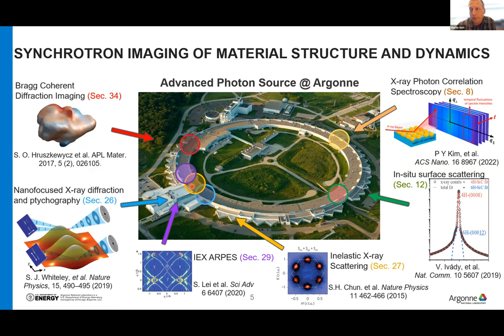And that's the point, to my mind, of creating these sources at these 1 angstrom wavelengths, is that your 10^-4 bandpass of that wavelength gives you access to strain at a fidelity of 10^-4 relative to this wavelength. So it's really orders of magnitude beyond what you can get with even the best electron microscopes, even though, of course, our spot size and scanning resolution are quite a bit larger, in addition to core level edge spectroscopy and the other things that Dylan was speaking to.